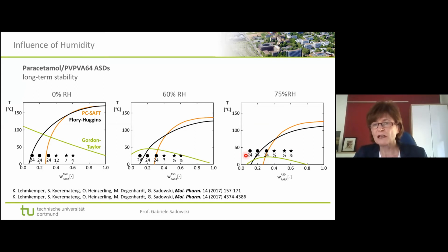And again, all the samples right of the solubility line did crystallize and all the ones left did not. So that means indeed that the solubility line should be somewhere between this and this sample. And this is also what our prediction says. So we are very happy with this. And this says that instead of waiting 2 years, waiting 1 year for this result and waiting half a year for this result, the prediction can tell in advance what will happen.